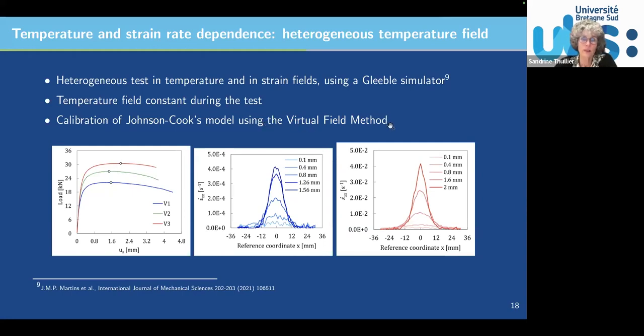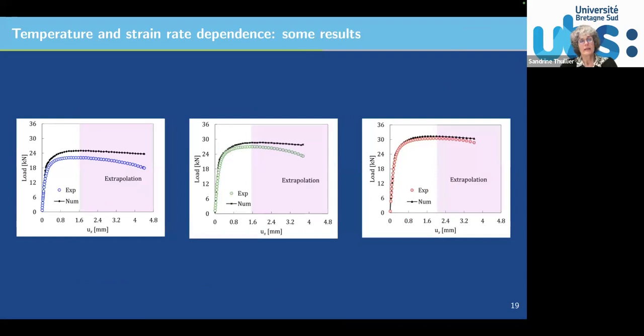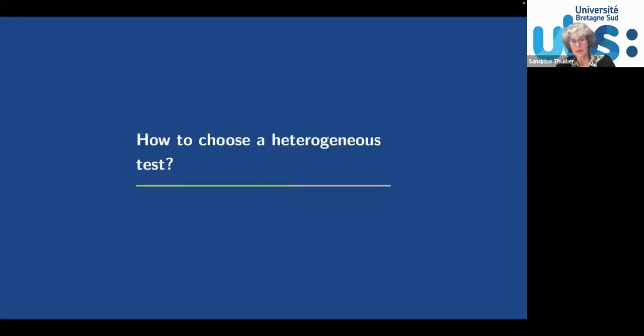In this case, the virtual field method was used, which is another method in order to calibrate the material parameters by inverse methodology. And so the load signal was used at 3 different speeds of the test, and the idea was to investigate and to characterize the strain rate evolution. So over a sample, you've got an evolution of the strain rate, and this information will help you to calibrate the model. So here are typical results. So you can see, well, in this case, quite a good description of the load. Well, it's not that good at this strain rate, but we also know it comes from the limitation of the Johnson-Cook model.